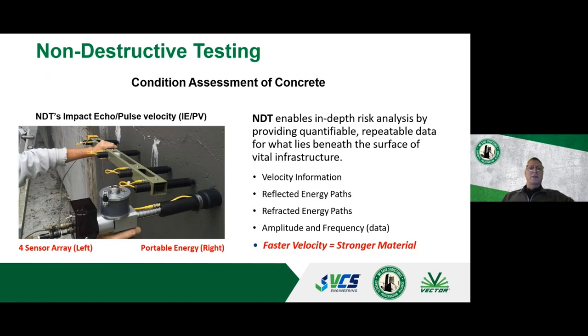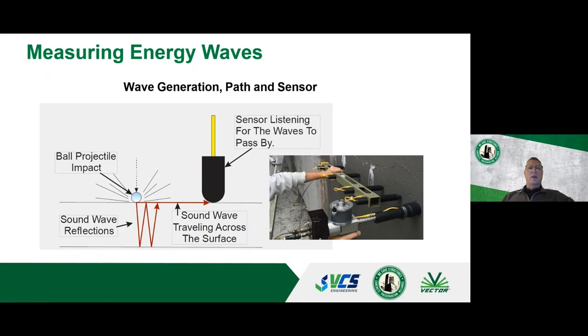So impact echo, the non-destructive technique, is a fantastic test. And I have some examples in the case studies to show you how useful this is. And it's extremely useful in thicker elements. So if you have piers, pier caps, bases, motor bases, whatever that may be, or thick elements as far as walls, what this process is, I'll get the drawing up here, is that you're creating a sound wave, an energy wave by impacting, by doing a projectile, and you're hitting that concrete with that projectile, a steel ball, at a high velocity. When that does it, it creates sound waves that travel through the concrete.